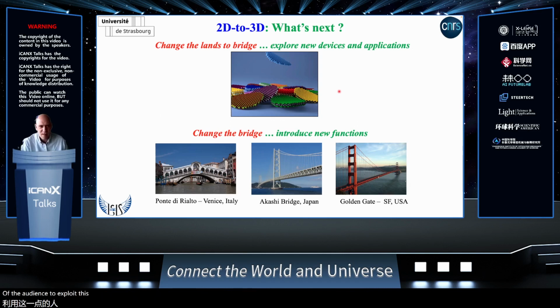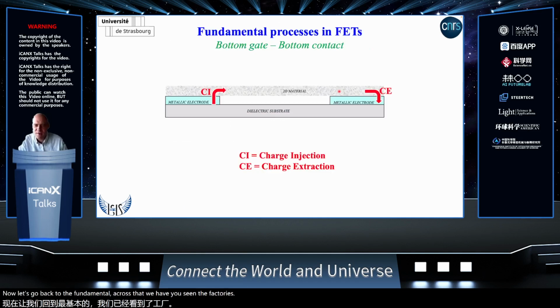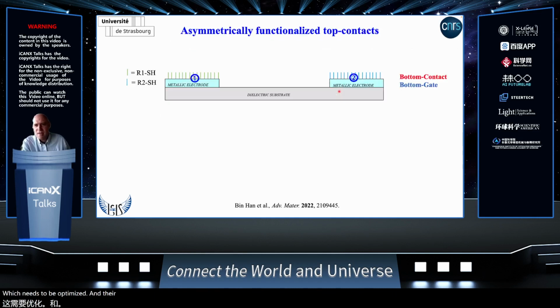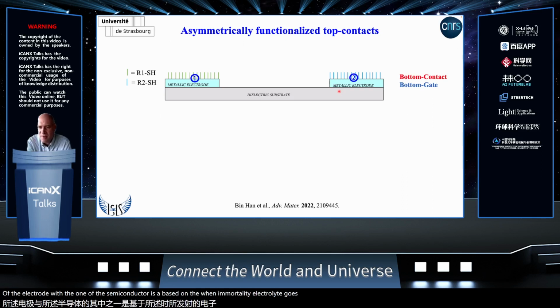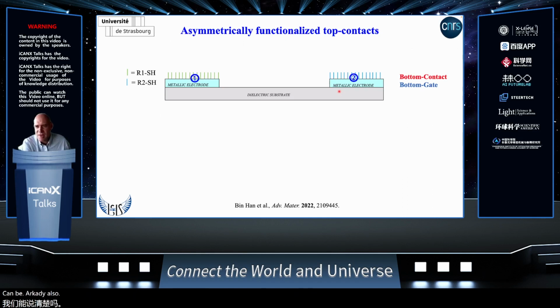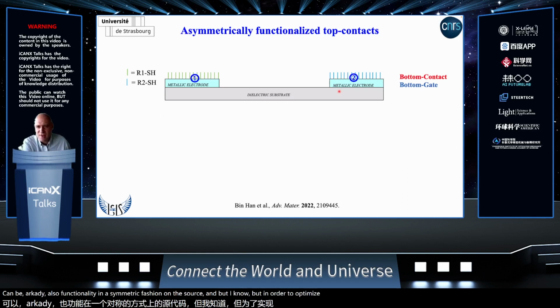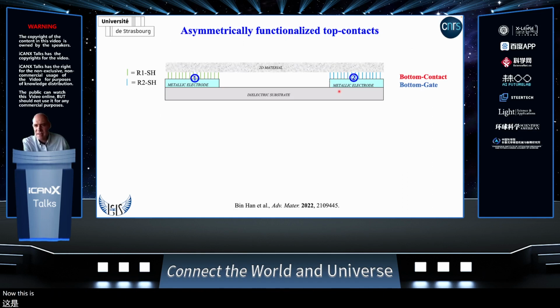Now let's go back to the fundamental process that we have in field effect transistors. In a bottom gate, bottom contact, of course, we have to deal with the problem of the charge injection and charge extraction, which needs to be optimized. And frequently, a way to do that, in order to optimize the work function, so the relative energetics of the electrode with the one of the semiconductor, is, when a metallic electrode like gold is employed, one uses a thiolated molecule with different types of end group, that can be R1 or R2, and can be functionalized in an asymmetric fashion on the source and drain electrode in order to optimize the injection and extraction.